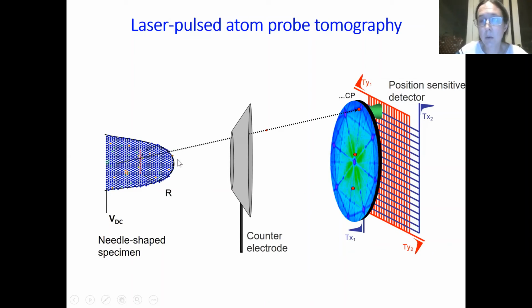We also want to know about the atoms going deep into the tip in the Z direction. But that's kind of simple because we basically get approximately one atom evaporating per pulse. The ones on the top have to evaporate before we can evaporate the ones further down. So the sequence with which the atoms arrive at the detector gives us their Z position along the length of the needle. So now we've got the positions of all the atoms.